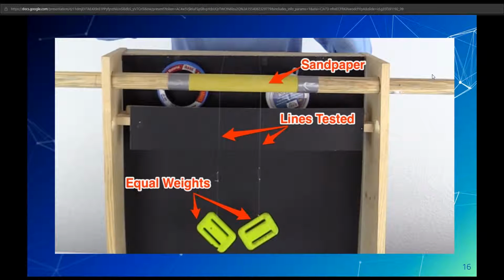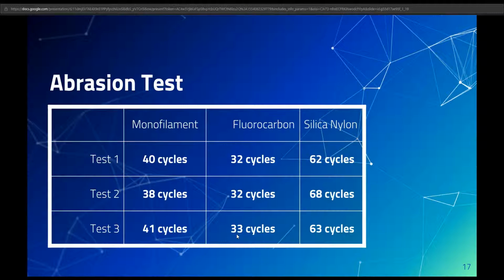We tested a standard nylon monofilament, the silica infused nylon, and fluorocarbon. They were tied to equal weights and were cycled back and forth on sandpaper until each achieved failure. The standard monofilament withstood an average of 39.6 cycles. Fluorocarbon came with the lowest amount of cycles resisted. The silica-infused nylon came out with the highest amount of cycles, resisting an average of 64.3 cycles.